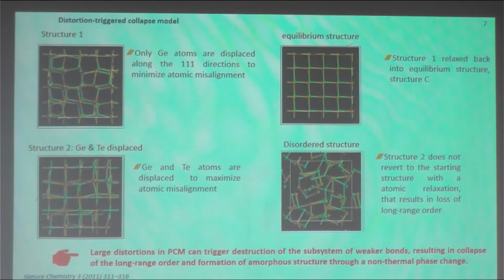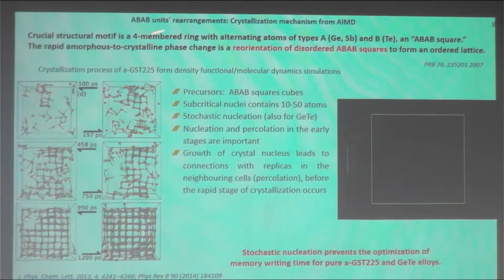So now the next model is based on ABAB units' rearrangements. Again, as I said, we know already that the amorphous phase consists of ABAB rings. A is germanium or antimony, and B is tellurium. And they make so-called ABAB squares in the material. Such squares also exist in the crystalline state, and this mechanism is based on the rearrangement of such squares to form an ordered lattice.